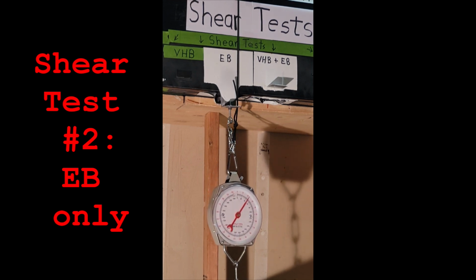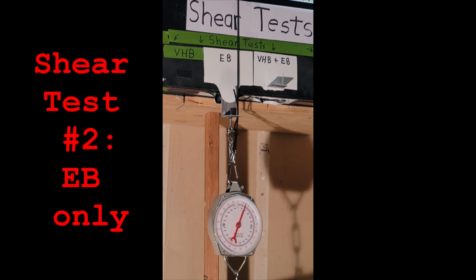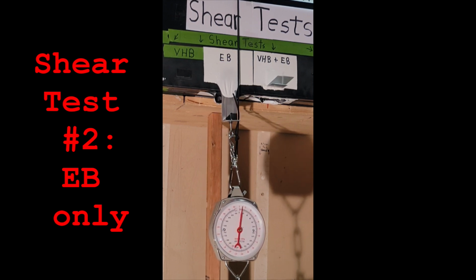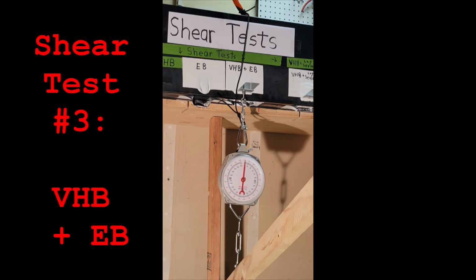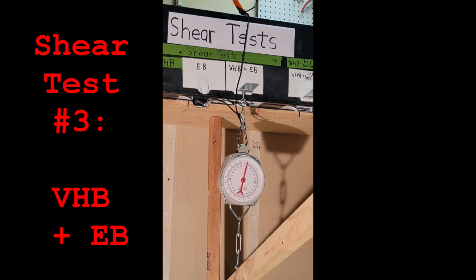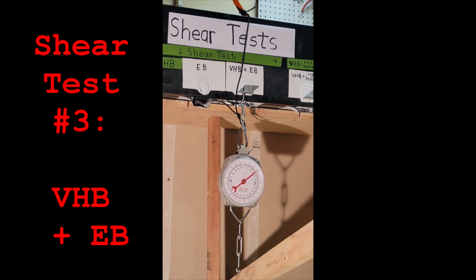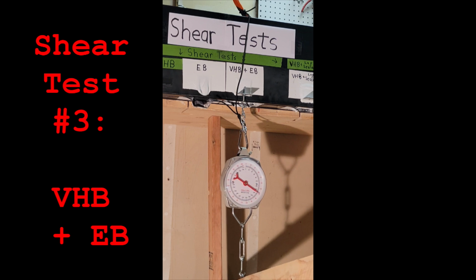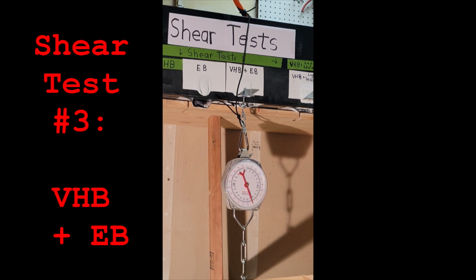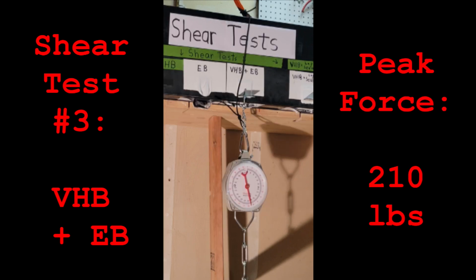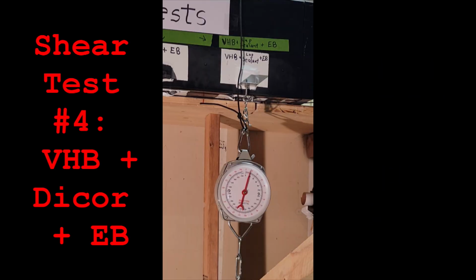Okay, it hit a peak and then it just started stretching. The max was 60 pounds. This is shear test number 3, very high bond tape plus Eternabond over the bracket and Dicor lap sealant along only the unsealed edge of the bracket. 210 pounds. Shear test number 4 has VHB, Dicor, and Eternabond on top.